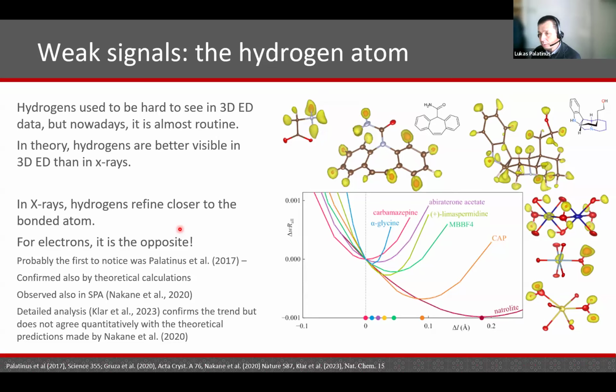So the question comes, what about electron diffraction? And the interesting outcome is that if you refine hydrogen positions freely from electron diffraction, the distance will be slightly longer than the nucleus distance. And the reason is that electrons are sensitive to both the negative potential of electrons and the positive potential of the nuclei. So if you shift the negative potential of electrons towards the covalent bond and keep the nucleus where it is, then the total sum, positive minus negative, will shift a little bit away from the nucleus.